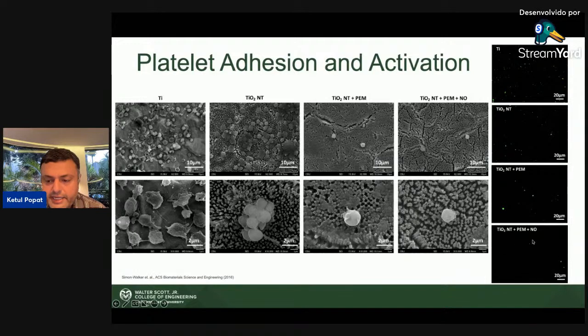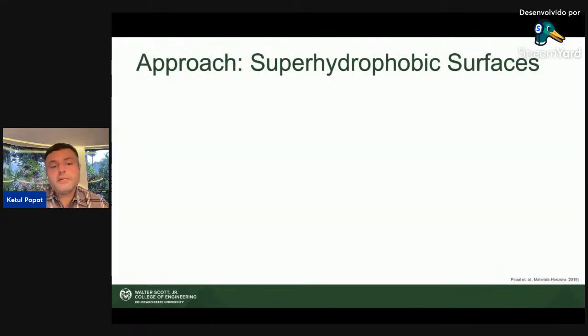We did not see any kind of platelet or white blood cells on the surface, which was actually pretty exciting. So you can see a lot of platelets when you have titanium, and you see a lot of platelets when you have nanotubes, but as soon as you have nitric oxide, practically everything is gone on the surface. We want a surface like this because it is not going to clot, and you won't have blood clotting problems.